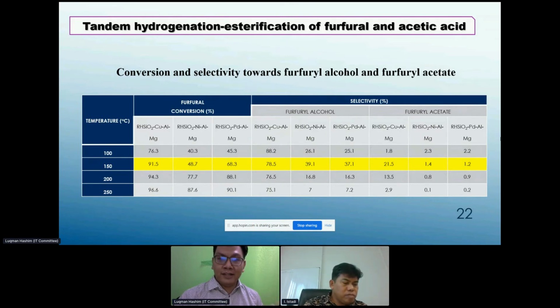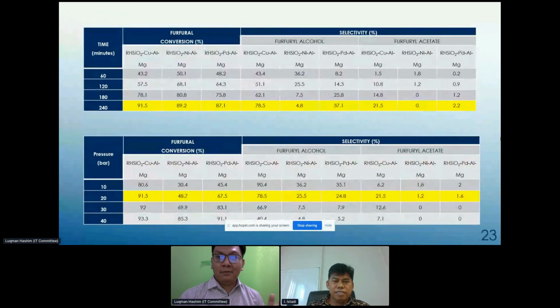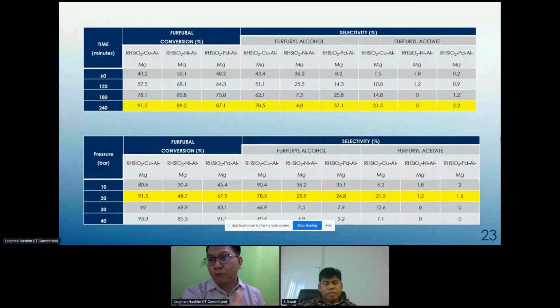For 200 and 250, I believe they are more inclined towards cracking and hydrodeoxygenation processes, which will lead to furan, as you saw just now in the past researches. The same can be said for pressure as well. A relatively mild pressure, 20 bar, is what we need for furfuryl alcohol and good furfuryl acetate production. As for time, generally, as you increase time, the product increases. However, that is not the case for some furfuryl acetate production in terms of nickel, because nickel is very prone towards production of hydrodeoxygenation product rather than hydrogenation product, due to its inherent attraction towards furfural's furan ring rather than its carbonyl carbon bond, which is what copper is actually very attracted to, as we discovered here.